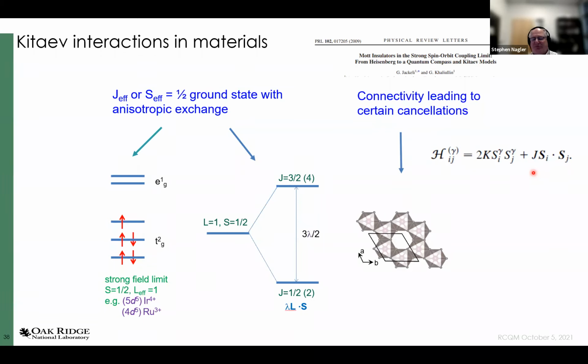Now, without getting into the minutiae, let me point out that, of course, here we have octahedra that are 3-dimensional. It's not, strictly speaking, a 2-dimensional system, but you do have a 2-dimensional lattice of magnetic ions in one layer. But in fact, the X, Y, and Z axes now are mutually orthogonal axes that when I project them onto the hexagonal plane, do form the 120-degree lattice. But you know, the actual spin axes are orthonormal, and they do have competing interactions. So for all practical purposes, this maps onto a Kitaev type interaction with some extra stuff.